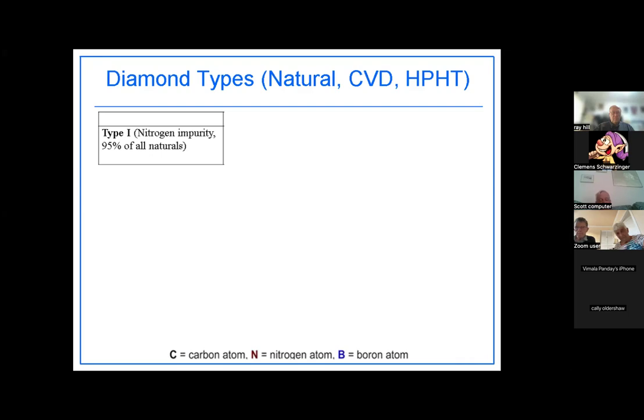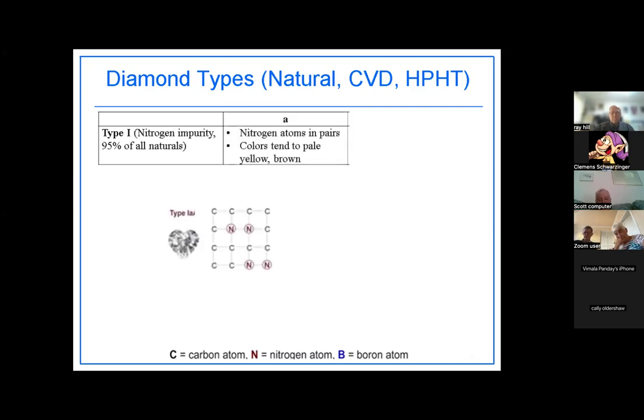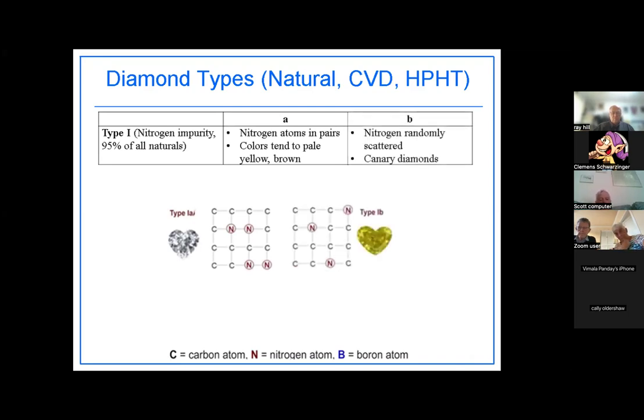Now, there are several diamond types, and I'm only going to talk about the predominant four. And it doesn't matter whether we're talking about natural diamond or lab grown in either of its forms. But your type 1 diamonds, this is 95% of all your natural diamonds, and they have a nitrogen impurity. And that nitrogen impurity usually gives them some shade of yellow. Now, a type 1A, your nitrogen atoms are in pairs, and this gives you your pale yellow and your brown diamonds. If you have a type 1B, you still have nitrogen, but you can see that they're randomly scattered throughout the crystal, and this results in your canary diamonds.